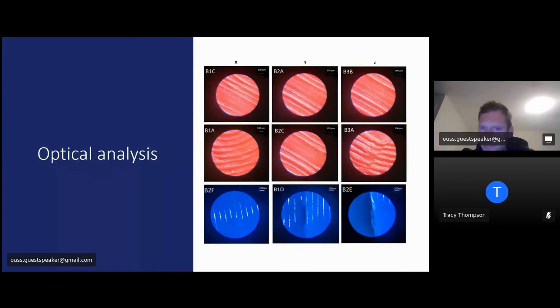And skewed. So they're no longer straight lines, they're curved. And this could be for a number of reasons, most likely due to negative gravity slump. So as Tracy said in her research, it could be down to a gravity slump. Well, there's evidence here of something going on in the same axis direction as the printed part. So this is direct evidence to show that actually gravity does have some sort of influence on 3D printing, because I'm showing slumping in the opposite direction now.